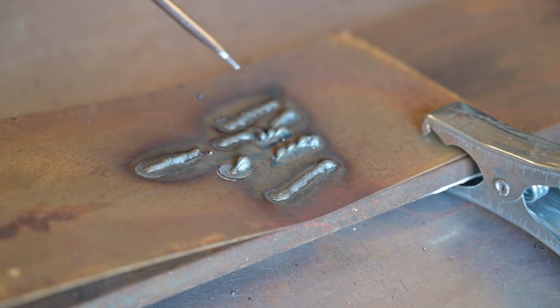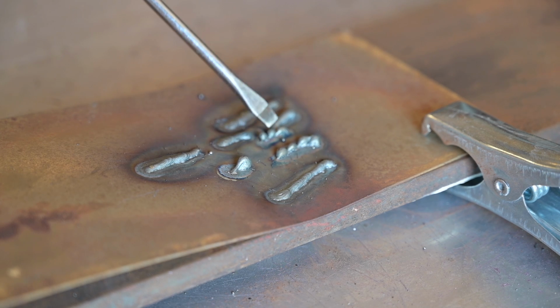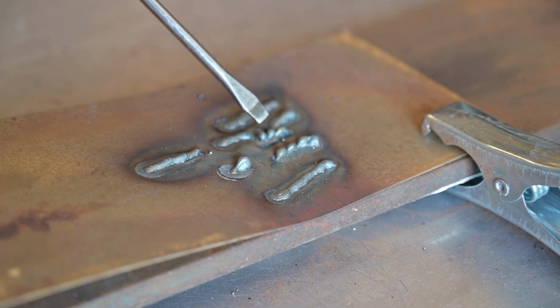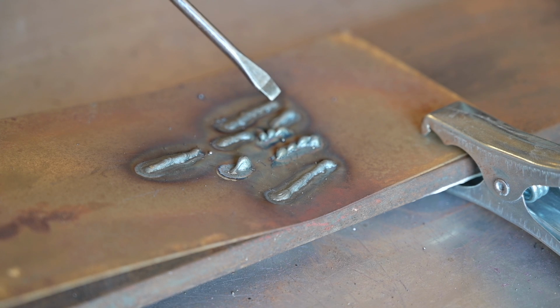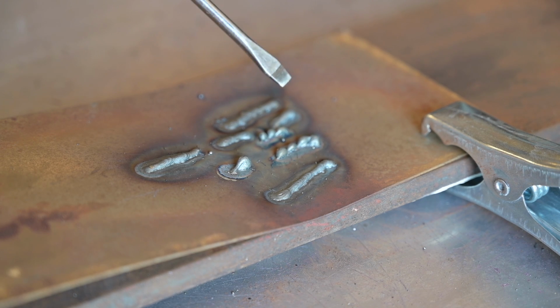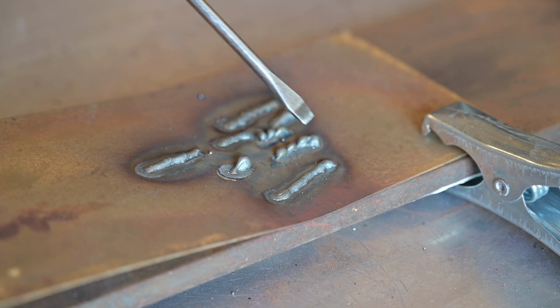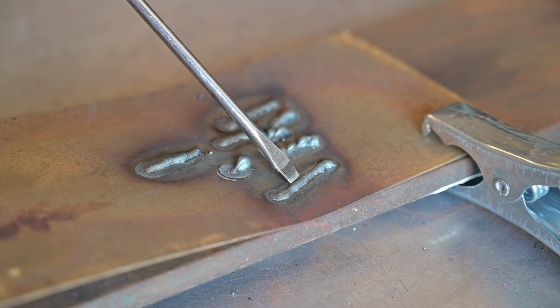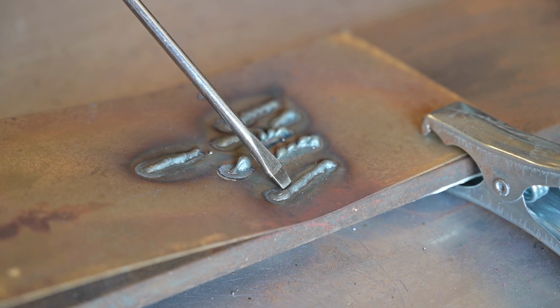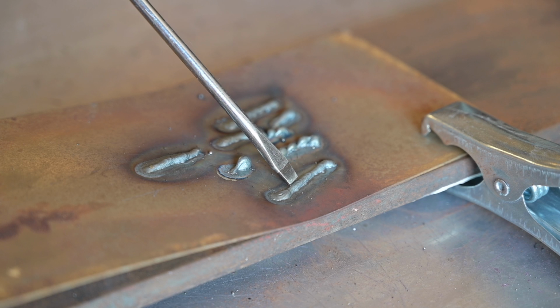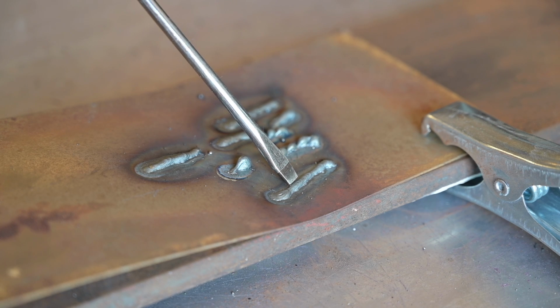So I did a few settings while we were trying to weld, and you can see the bubbles here. That's really not good at all, but that was because the wire speed wasn't right. It was too slow, so the wire burns too quickly and it doesn't get enough feed. At the end, I adjusted everything, and here is that weld, and it's very short weld, but this is a lot better, and this is how it should be once everything is properly adjusted.